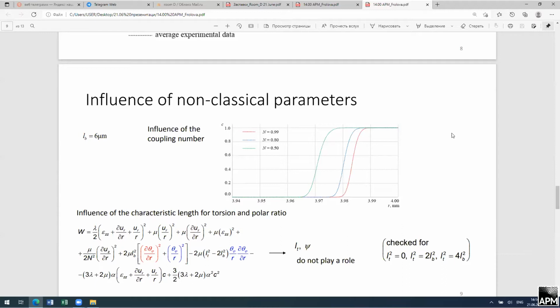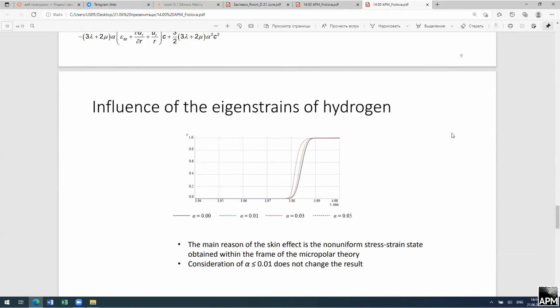And here we investigated influence of non-classical parameters, namely coupling number, characteristic length for torsion and polar ratio. Here we can analyze expression for the elastic strain energy. There is no polar ratio, so it shouldn't play a role. And also we can see that characteristic length for torsion is multiplied by blue terms that are less than red term according to asymptotic assumption. Therefore, it also shouldn't play a role, and we have checked it and obtained that yes, all these constants don't play a role, so only coupling number and characteristic length for bending can affect the solution.